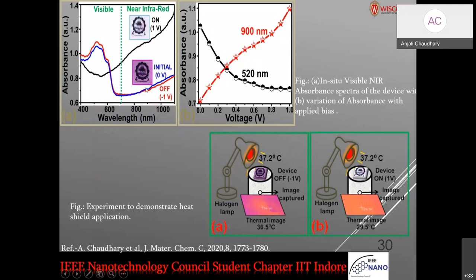Initially, we got only 0.1 absorbance fraction without using tungsten. But by using this, we got nearly 0.7 absorbance improvement. So this is at various wavelengths. This is a visible one and this is a near IR one. So when we apply a bias, this goes on decreasing and this goes on increasing.